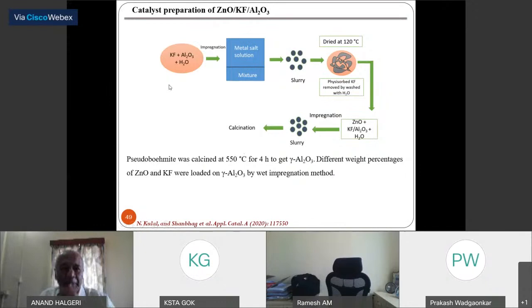The next class of compounds which we did in our institute is a basic material called potassium fluoride supported on alumina and water. This is done by metal impregnation on alumina, which forms a slurry, and dried at 120 degrees centigrade. Potassium fluoride is absorbed and then removed and washed. It forms a mixture of zinc oxide, potassium and alumina. Then it forms a slurry, and then activation gives the final material. Pseudoboehmite was calcined at 550 degrees centigrade for 4 hours to give the alumina catalyst.